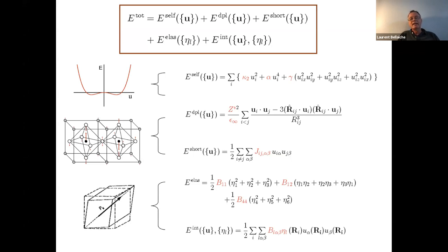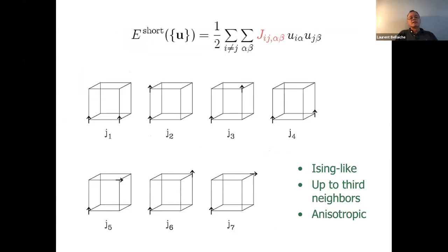And what I indicated in red here are all the coefficients that you get by performing first principle calculations. So these are general equations, but when you go from one system to another one, what changes are basically these red coefficients. And you can get them from first principles. For instance, if I look at the short range interaction, one of the seven energies, you see they are quite different. You have the one we call J1. It's the interaction between two dipoles that are oriented along the Z axis, but that are distant along the X axis.